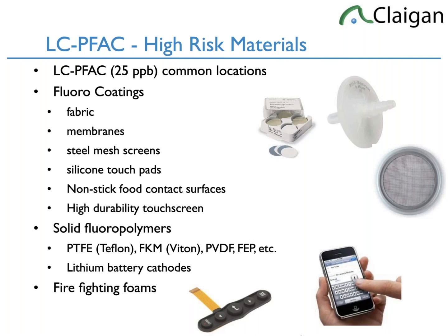Your lithium battery cathodes, by the way, are PVDF. So they can have it too. Doesn't mean they have to. Fluoropolymers can be made without it. It's just really easy to use PFOA or PFNA to make Teflon. By controlling the concentration of PFOA, you pretty well control the grain size, the precipitation of the PTFE when it's manufactured. Very easy way to control it. That's why PFOA is so useful.